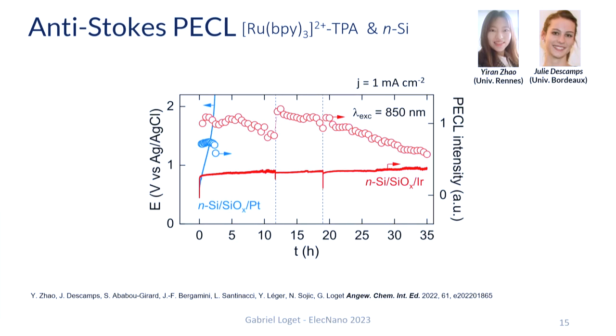But for iridium, it works very nicely. As you can see here, the potential of the electrode is stable for more than 35 hours, and the PECL emission can last for a very, very long time. So this shows that by applying the proper protection layer, we are able to make this PECL system last for a very long time, which was very important for us.